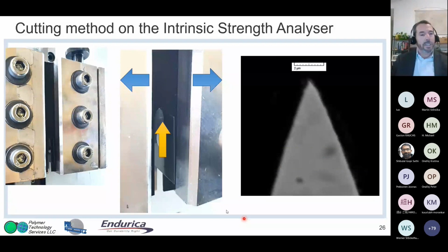Basically, if you look at this, this is a planar tension specimen, but it's turned sideways, right? It's turned vertical, and there's a cut in the specimen into which there's a blade that's pushed. So you can see it much better here. So here's a blade. So we still open the crack like you would normally for a tear strength measurement or a fatigue crack growth measurement.